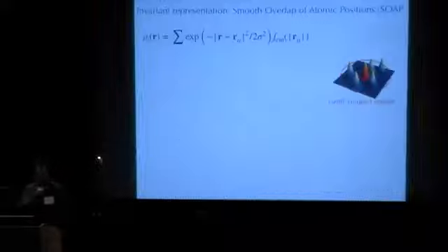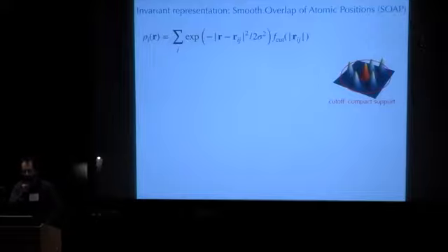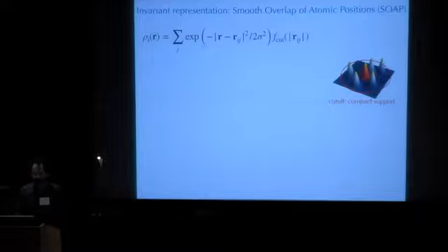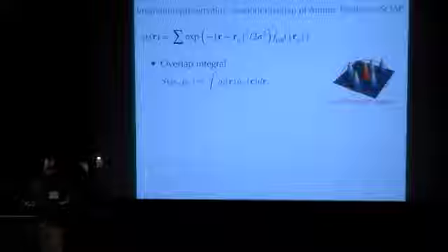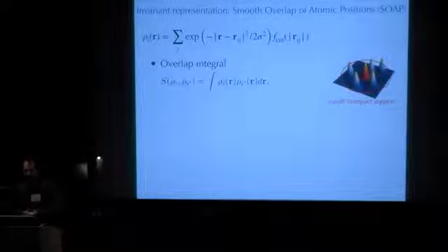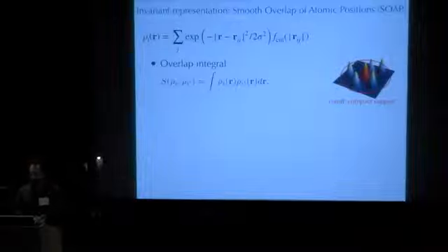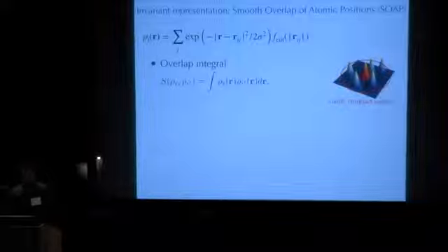So we're going to use kernel regression. And here's the kernel that we've built up over the last few years that has served us very well. We're going to represent the neighborhood of an atom. Here's an atom. Here's the cutoff. And within it, there are some atoms. And we're going to represent it as a density. It's a Gaussian-modified density with a finite cutoff. And then the kernel between two different environments, which is what we need to do kernel regression, is going to be the overlap between these two densities. And that solves permutation invariance.